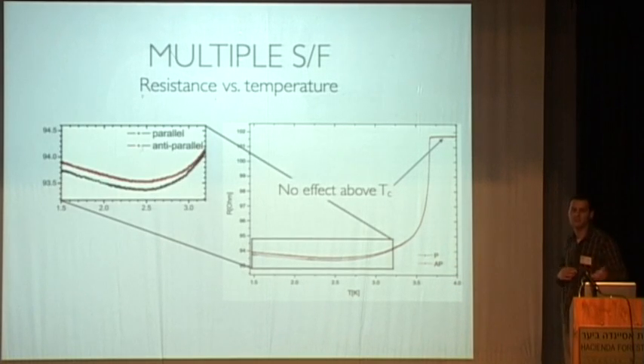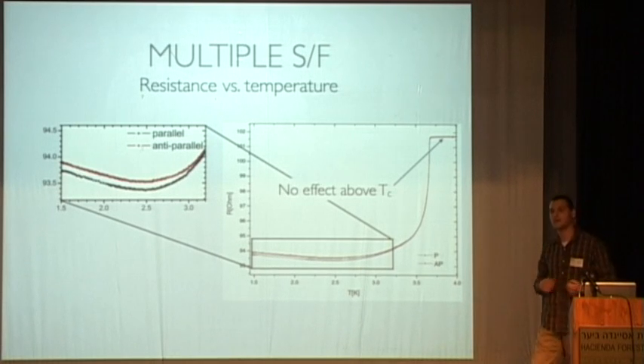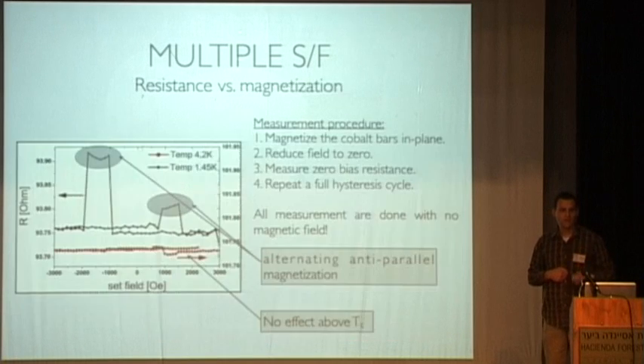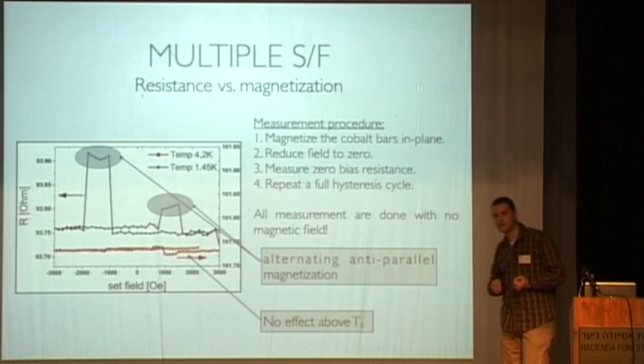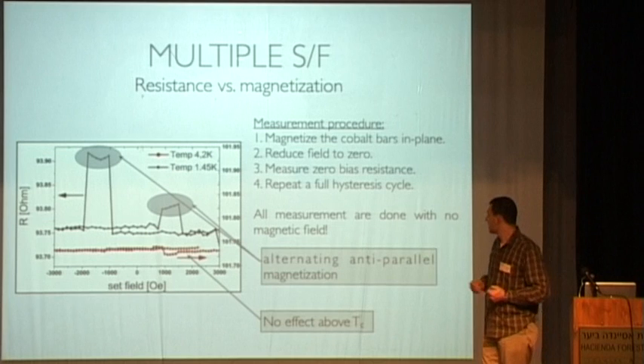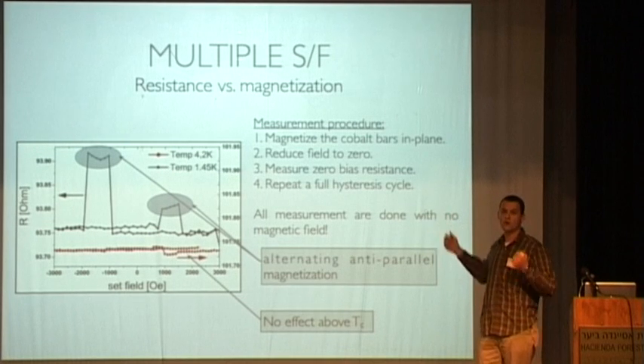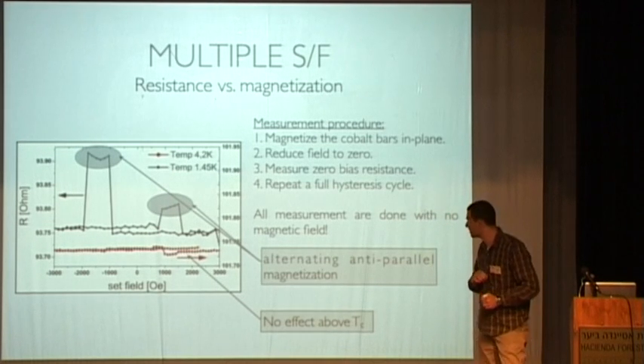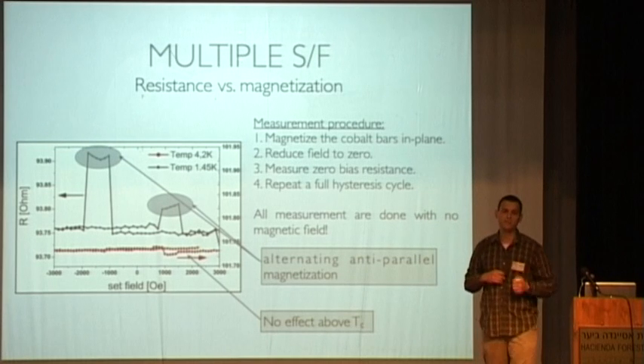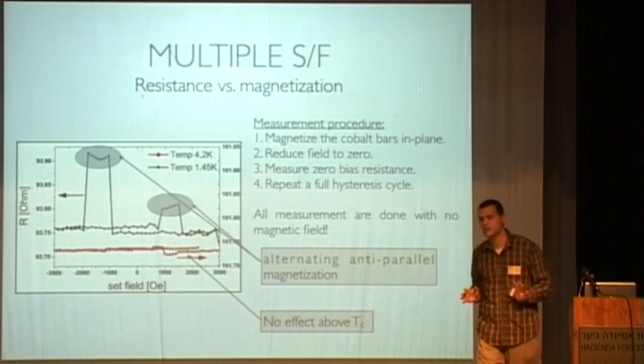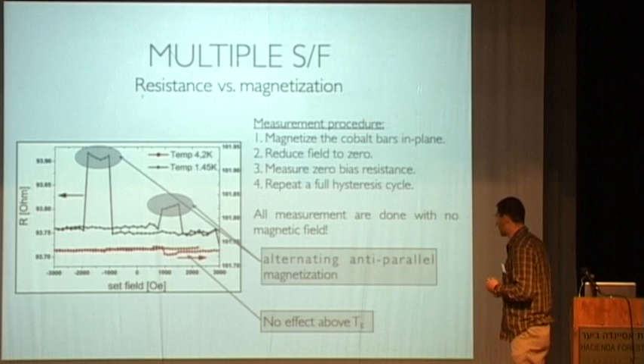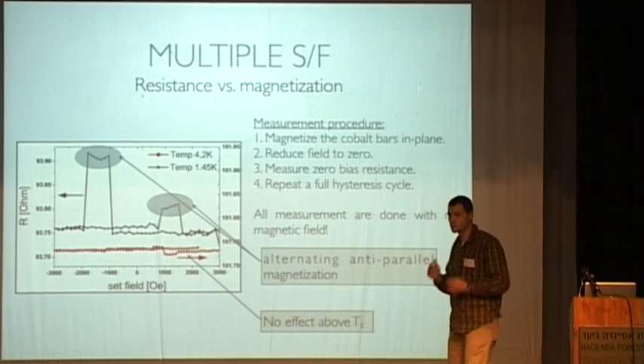And it turns out that if you see here the resistance, you see a difference only below TC. You see a difference between the parallel and anti-parallel configuration. Again, the parallel configuration is preferred. It has a lower resistance. And we verified that this is really a magnetic phenomenon. You see the two states happen only at anti-parallel configuration and happen only below TC. So this is not purely magnetic. It has superconducting origin, these two states.